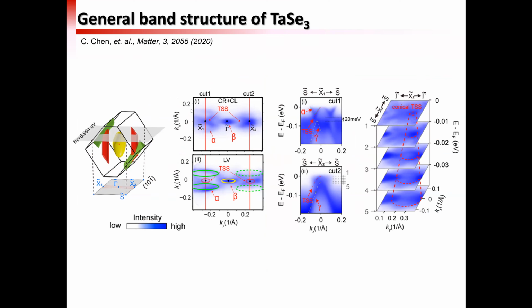But in addition to these bulk pockets, we also see something more; definitely we see more than 2 Fermi surface pockets. Then what are those? Our guess was that these are the surface state. And indeed, if we do the calculation, we were able to find it. If you can see my cursor here, the calculation shows the broken red line is this topological surface state, and that was discernible from our measurement. You can see it's also from this dispersion, and also from this constant energy contour plot.